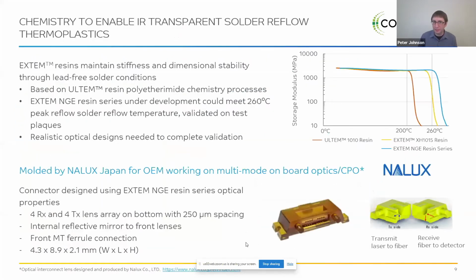The second thing that we wanted to actually focus on was building new chemistry, because there were certain limitations that we've seen with ULTEM. And we built this EXTEM resin portfolio, and the whole goal of it is to maintain stiffness and dimensional stability through lead-free solder reflow conditions. It's still based on the ULTEM chemistry process. And what we were mainly focused on was getting something that could meet 260 degrees C peak reflow temperature.